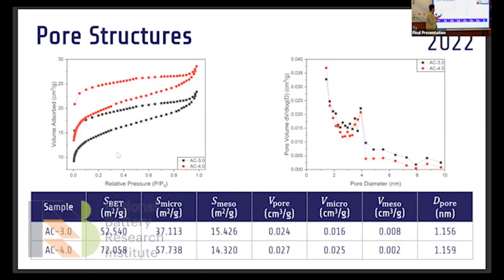Next. This slide presents the pore structure from PSA. It can be found that AC3 has a weaker volume adsorbed than AC4, resulting in a lower surface area and pore volume. It could happen due to the long activation time that ruins the pore structure. However, it does not affect the pore diameter of around 1.2 nanometers. The inspected pore size distribution proves the presence of micropores and mesopores. These pores are suitable for supercapacitors because of the efficiency of the charge storage mechanism and ion transfer.